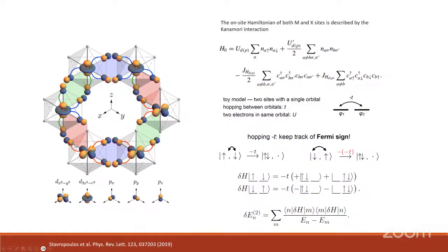However, along this side, even though the d-z-squared orbital is able to overlap with the pz orbital in this plane, on the other side, if you consider the p orbital overlapping with the dx squared minus y squared orbital, then the other path is broken, because the d-z-squared orbital is hard to overlap with any p orbitals in this plane.